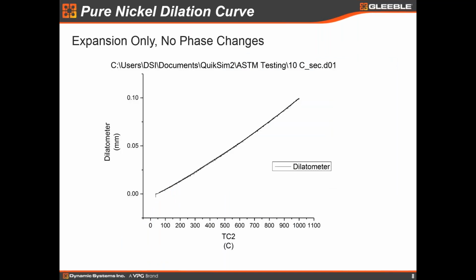So I'm just going to move on a little bit to the actual data that we get out of the dilation plots here. This is an example of a pure nickel sample that's heated from room temperature to about, I think, 1050, 1100 C here. And this is a simple thermal expansion curve for nickel. It shows no phase changes. And so this is about the simplest dilation plot that you can get.